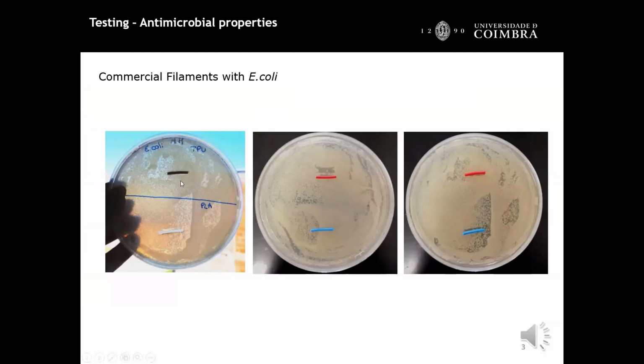In fact, we have here the tests for Escherichia coli, and we have TPU. Let me just put the laser. Okay, and we have here simple pristine TPU and PLA, and as you see, the bacteria grow because they are not antimicrobial. The composites with copper of these polymers, if you take them away from the place where you put them, you see that no bacteria have grown. So the filament has in fact antimicrobial or antibacterial properties.